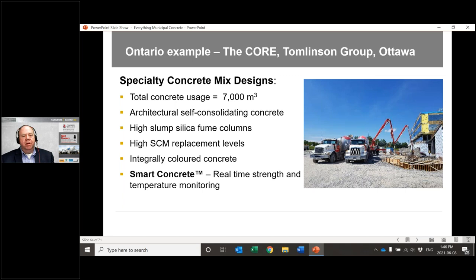But again, they were looking for ways to optimize the mix. So again, they're looking at high performance concrete, using self-consolidating concrete where applicable to try and bring the thickness of elements down, using SCMs wherever possible, putting color into the concrete and leaving exposed columns and floors open as much as possible to reduce other construction materials, and then even using things like internal concrete temperature sensors.